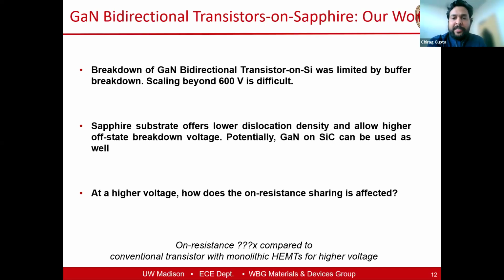One of the key questions, which I was very interested in, and that's why I wanted to move to higher voltage, was to see how this sharing is affected. Basically, at 600, 1200 volt range, and if we look at other reports, nominally it's somewhere around 50% extra resistance that we were seeing, give or take a few tens of percentage, but there is some advantage. So the question I asked myself is, if I go to a higher voltage with GaN HEMTs, with GaN bidirectional devices, does the ratio move towards better sharing, or does it make it worse? And how does it compare to unidirectional transistors? I was very interested in seeing how far this can be pushed before other challenges start to happen in these devices.